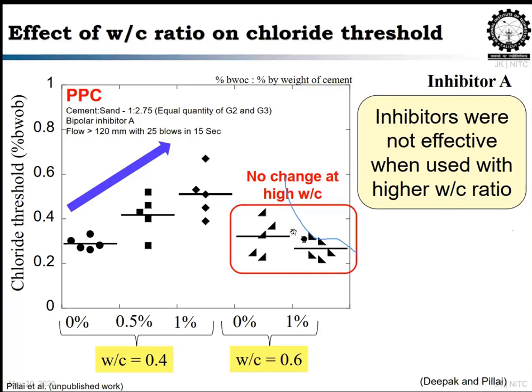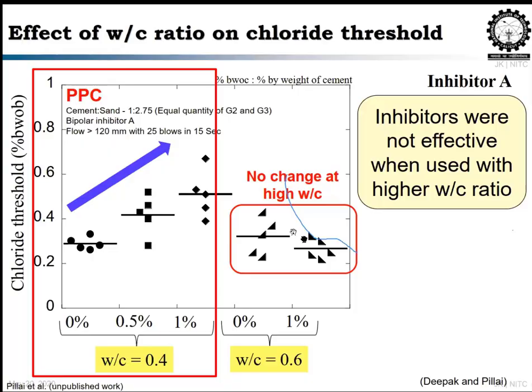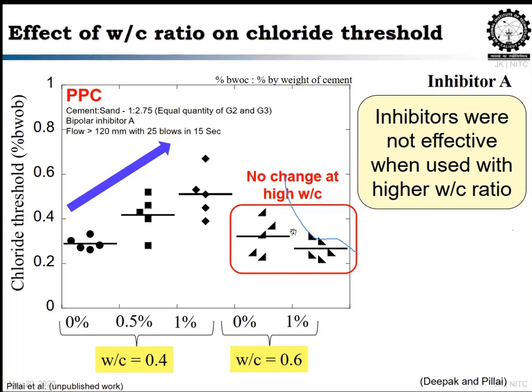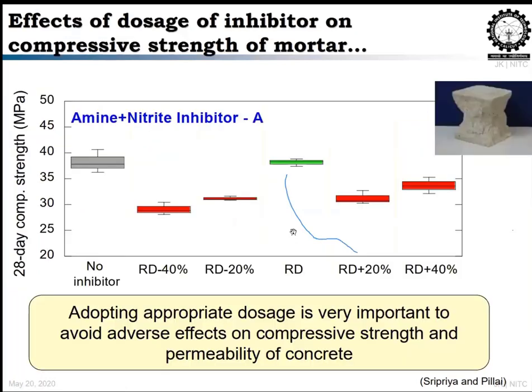So it is always recommended to go below 0.5 water cement ratio if you are using any inhibitors, not only bipolar or anodic inhibitors, any inhibitor. It's always better to go with 0.5 water cement ratio, and you can get your slump with your classes. You can play with that.